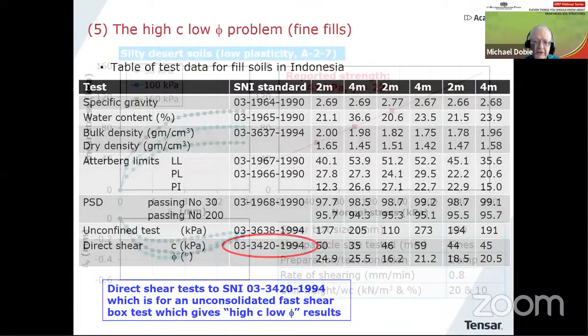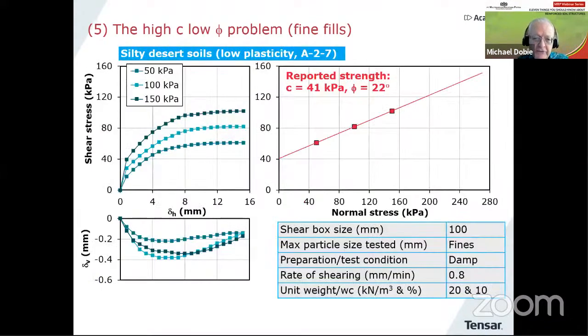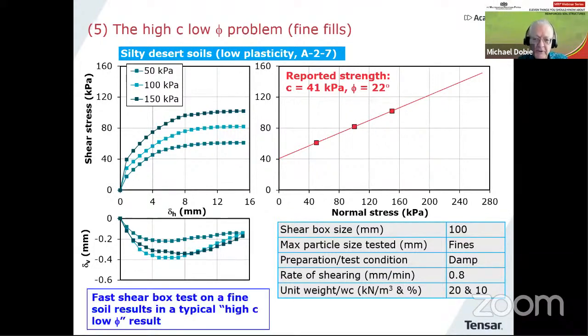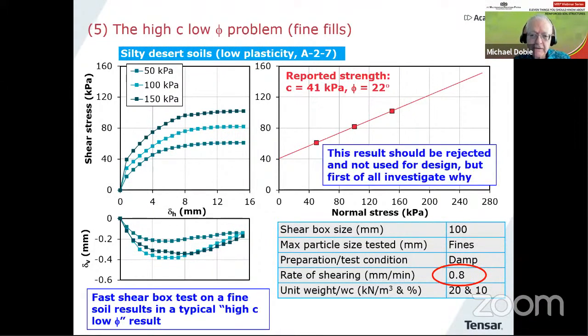And if you want to look at an actual test result like this, here is a fairly fine soil. It's an A27 soil, low plasticity soil. It's a desert soil in this case, but this is a fast shear box test. And how do we know that? Because if we look at the table of data there, we can see the rate of shearing was 0.8 millimeters per minute on a fine soil. So what do we get? We get this kind of behavior, high C, low phi. Now, if you're presented with that data to design a reinforced soil structure, you shouldn't use it. You need to make some kind of reassessment and try to decide what would be a suitable C dash and phi dash to use, maybe based on index testing.